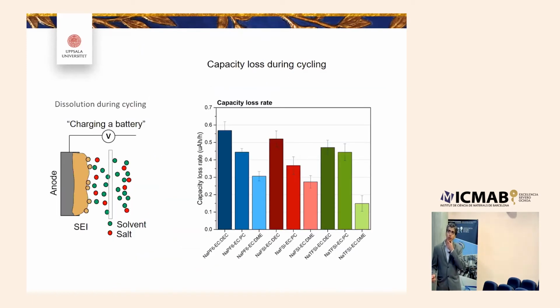Some of the results we have got so far indicate, as expected, this SEI dissolution is very much dependent on the salt and solvent chemistry. We tested 3 different salts, PF6, FSI, and TFSI, in 3 different solvent mixtures, either ECDEC, ECPC, or ECDME. What you see here is that no matter what salt you use, ECDME provides the lowest capacity loss due to this SEI dissolution. So that's one of the conclusions here.